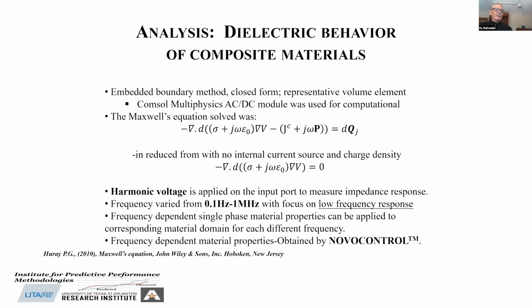There are only two things inside of that parenthesis. First, a subsequent set of parentheses that has sigma plus i omega epsilon 0. Epsilon 0 is our representation of the dielectric permittivity. Sigma here is the electric conductivity, thought to be small for these materials, but sometimes not completely 0. Delta V is what change in potential as we apply our field from point to point in whatever material volume, control volume, that we're analyzing.